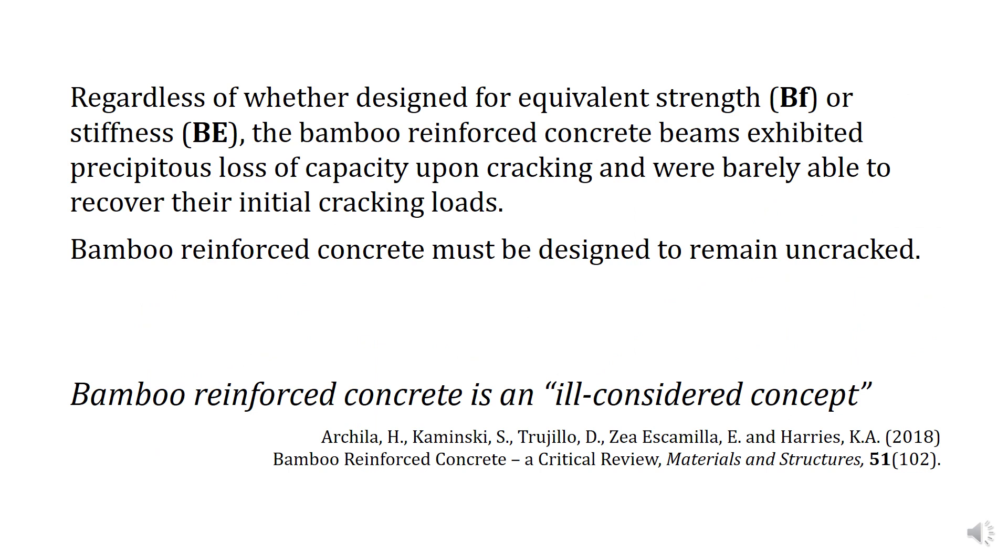So regardless of whether designed for equivalent strength or stiffness, the bamboo-reinforced concrete beams exhibited precipitous loss in capacity upon cracking and were barely able to recover their initial cracking loads. Bamboo-reinforced concrete must be designed to remain uncracked.